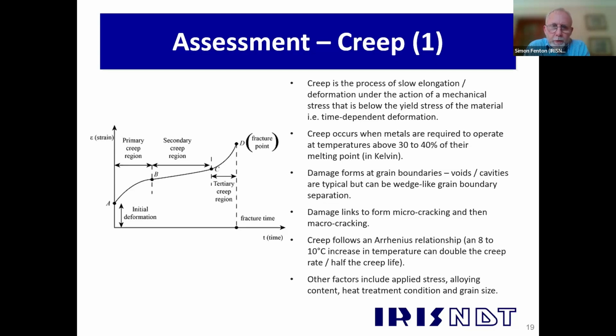And then a lot of components will spend most of their life going from B to C in what we call secondary creep. So this is a steady state creep, sometimes called. And the creep damage is starting to form during that period. And then when the damage starts to accumulate and form those micro cracks, we move into the tertiary creep stage, and then on to final failure at point D.